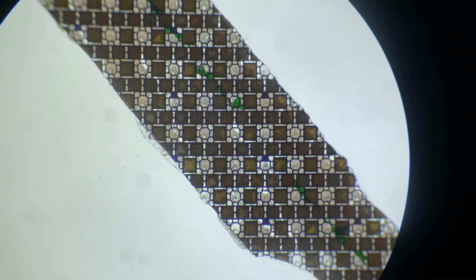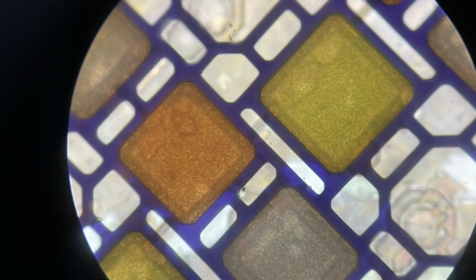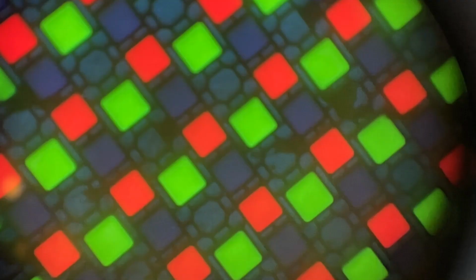And finally, we'll look at the quantum dot layers only. This piece happened to separate when I broke the pieces off the TV, and you can see this interesting sort of honeycomb structure holding things together. This appears to be the red, green, and blue subpixels, so the red and green are the quantum dots. And presumably this is where these materials are inkjet printed into this type of honeycomb lattice, if you will, to hold the quantum dots in place, to keep them in each of their respective subpixel locations. Here the same device is lit up with a UV flashlight. You can really see the green and red emission.